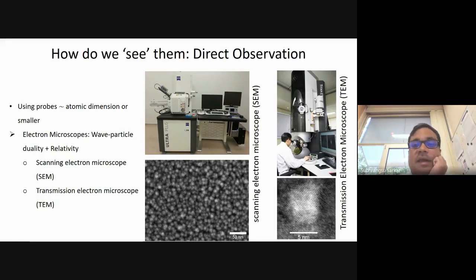Unlike the scanning electron microscope, it uses a much more energetic electron beam of about 300 kilovolts, and it can go down to sizes as small as one single atom. In this picture in the middle, I have produced one scanning electron micrograph that I took for one of my samples. And using a scanning electron microscope, which uses an electron beam of, let's say, the energy of about maximum 30 kilovolts, we can go down to 2 to 10 nanometer easily. Not easily, but we can go down there. I mean, people do it routinely.